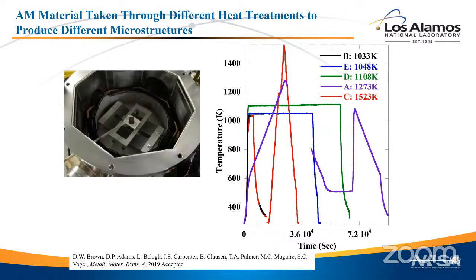And we're going to heat treat them in situ. We do it in situ so that we can watch the microstructure feature changes. So sample E, for instance, was heat treated to 1048 K. We heated that up and we're watching the ferrite fraction change and we're watching the dislocation density change. And I'll show you in a minute that the ferrite actually goes away first. I hope I'm saying that right. In a minute, we'll know for sure.